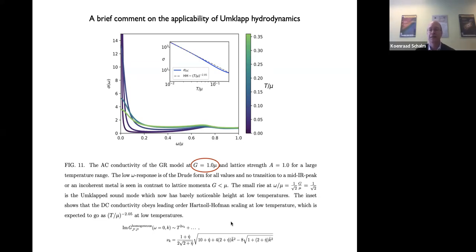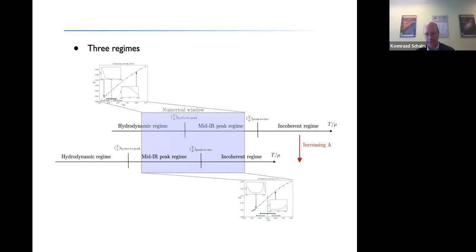So it's important for this scenario that I've described, with this Umklapp hydrodynamics where I have a mid-IR peak, that the lattice vector of the lattice is smaller than the chemical potential scale where hydrodynamics sets in. So I've now explained this transition between this hydrodynamic regime and this mid-IR peak regime. You can understand this from Umklapp hydrodynamics, where you have this extra Umklapp charge diffusion peak. There's a specific temperature at which this Umklapp charge diffusion peak collides with the ordinary Drude peak. The 2 poles can move off, and that gives you a mid-IR peak regime.